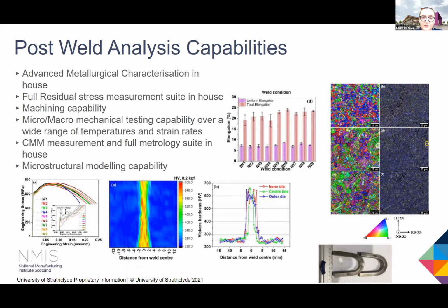So in terms of post-weld analysis capabilities at the AFRC, we have an advanced metallurgical characterization suite of equipment, as well as a full residual stress measurement suite. And actually we have a dedicated materials characterization and residual stress team in-house. We also provide machining capability, so we can create our own weld rings. We can also extract samples for post-weld analysis. We also have micro and macro mechanical testing capability over a wide range of temperatures and strain rates. So temperatures being from just below room temperature up to 1,200 degrees C, and strain rates from maybe 10 to the -4 up to about 200 per second.